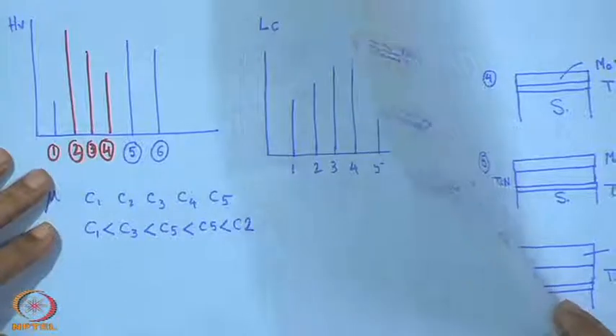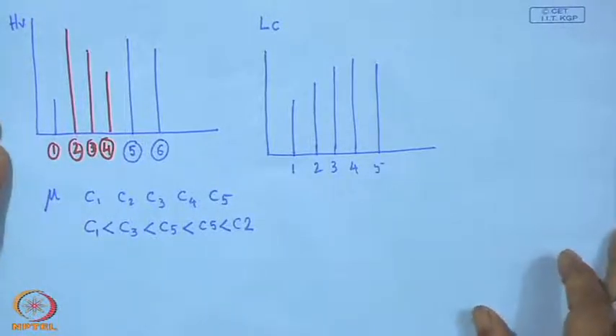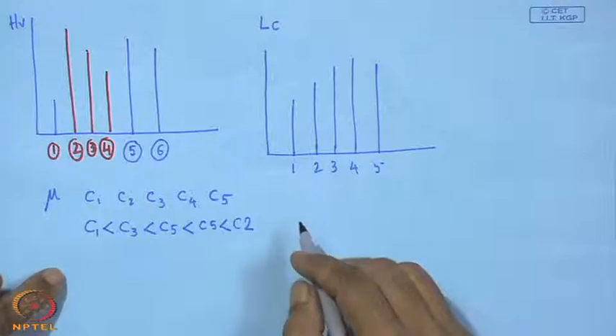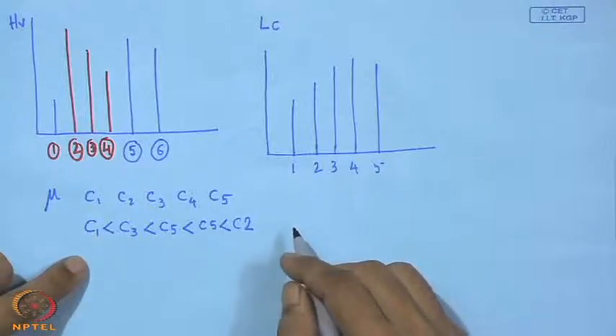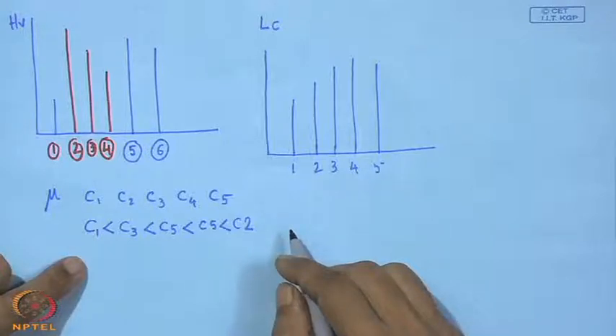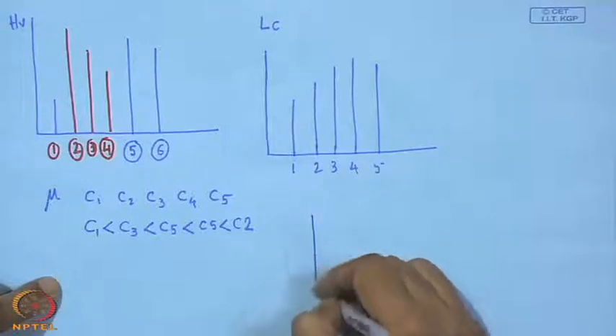Now, apart from that, what is also important for us to know is called wear coefficient. Wear coefficient is actually the wear on the track, that means on the disc which is coated. On that disc we have a wear channel, and from the depth of that channel we can determine the wear coefficient. We have already discussed that it is the volume of the wear on that circular wear track, divided by the normal load which is applied times the distance traveled by this normal load. So, from that point of view, we can just show this thing.